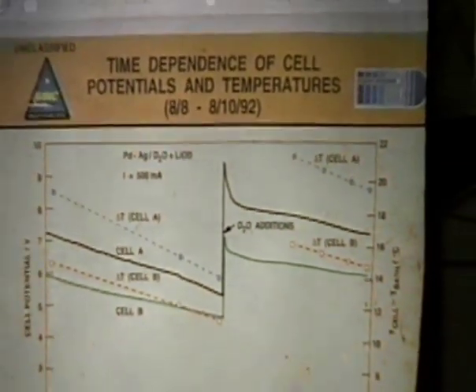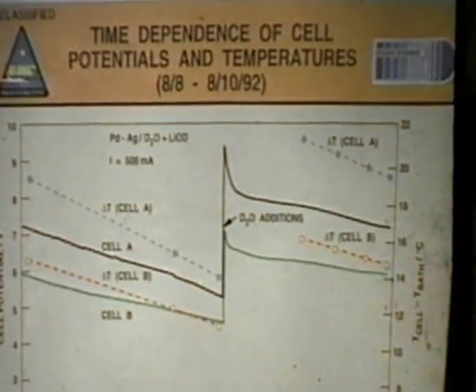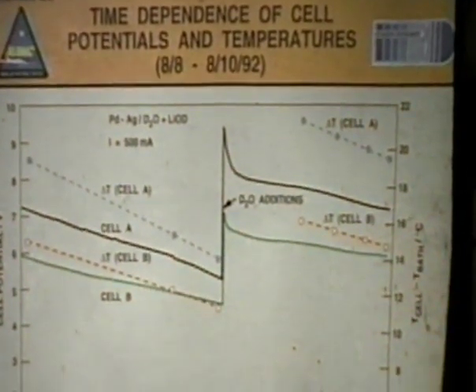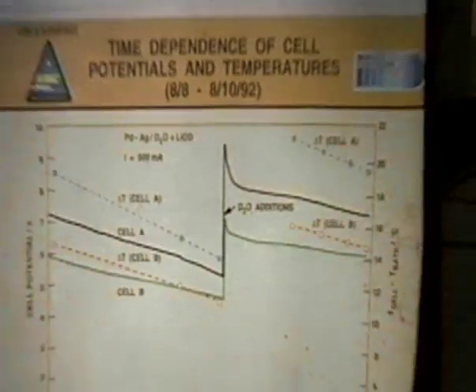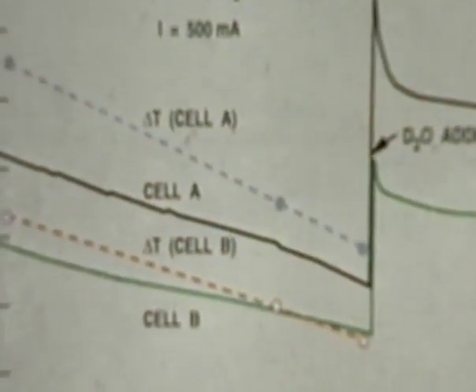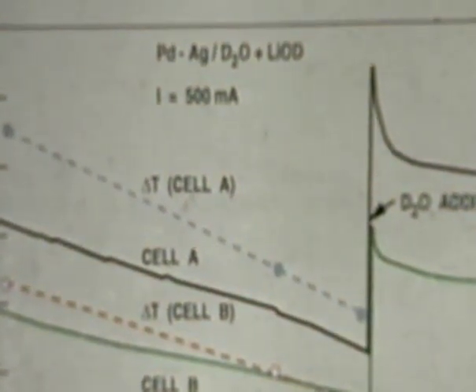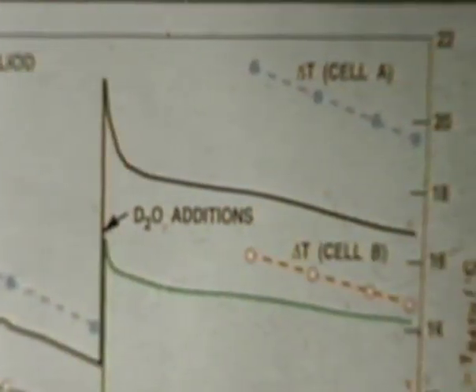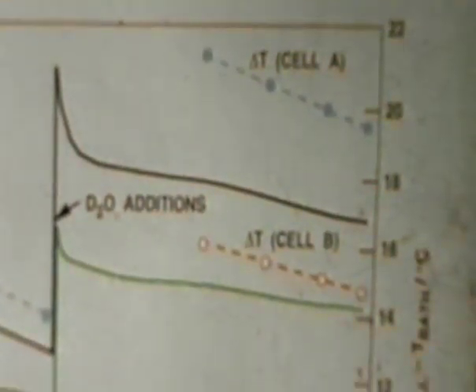There's no steady state in the calorimetry. As you can see here, the cell voltages are always changing, the temperature is always changing. So this just points out that there's not a steady state. We add the D2O, and there's a big increase in the voltage, but the temperatures and voltages do change in a linear fashion, which helps us evaluate the calorimetry.